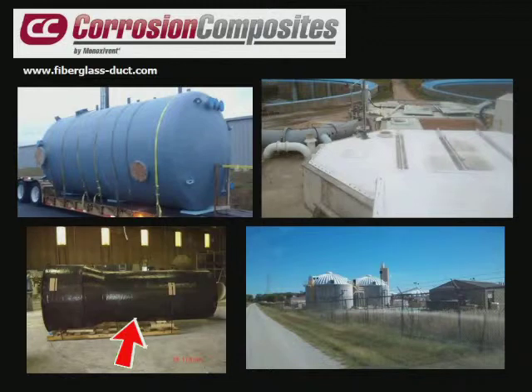The upper right-hand corner, we have some typical flat covers. And these are at the Cedar Rapids, Iowa wastewater plant. These have been in service about 5 years. They have another type of core called a Nida-Core. It's a polypropylene honeycomb, and it covers all of the flat panels and makes it so that a man can walk on it, takes the 45-pound snow load, etc. Yet they stay lightweight and can be lifted off.